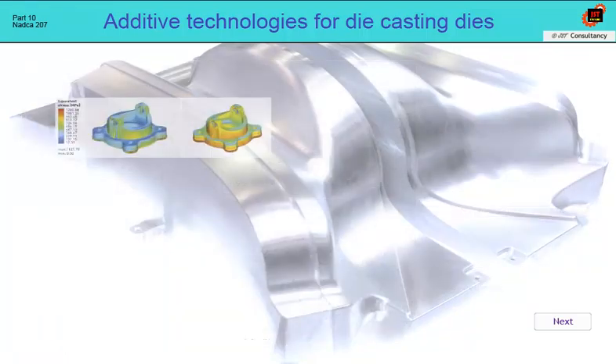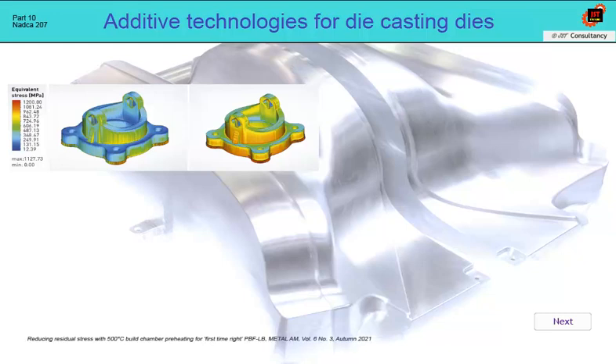Heating to 500 Celsius significantly reduces the stress in the printed product and at the same time reduces the effort to bend. On the left of the picture is the prediction of internal stresses in a body made of titanium alloy Ti6Al4V material at a substrate plate temperature of 500 Celsius, on the right side at 200 Celsius. Internal stresses are significantly lower. It is the same with deformations.